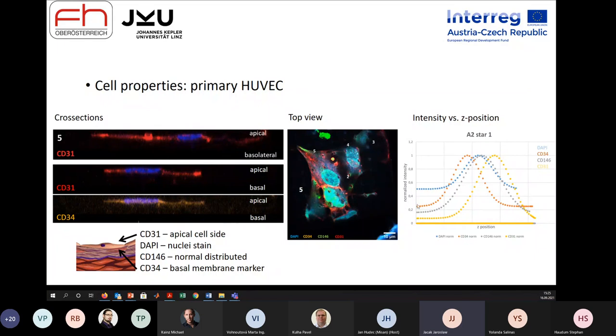You see nicely, this is a plot which describes the stains. So CD34 was here, CD31 was here, and this is a profile of a cell membrane. So this is the lower membrane, this is the upper membrane, this is the nuclei. Which means, if you look at this, should be the middle of the cell, the Z position. You see that CD31 was more expressed on top, and CD34 was more expressed in the bottom of the cell, which basically introduces a polarization.